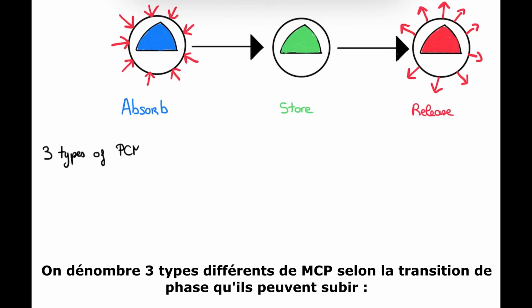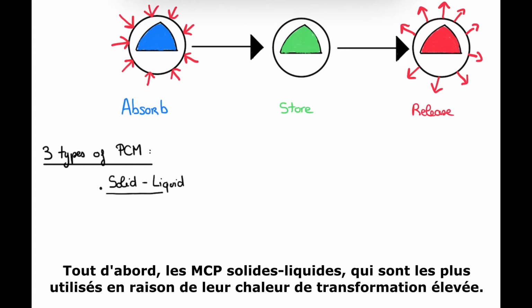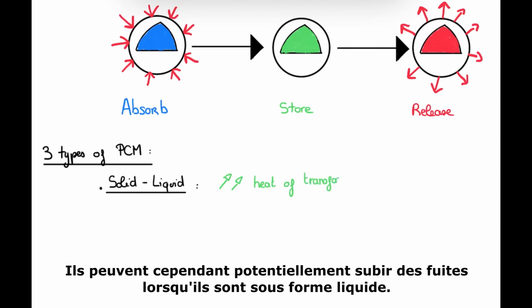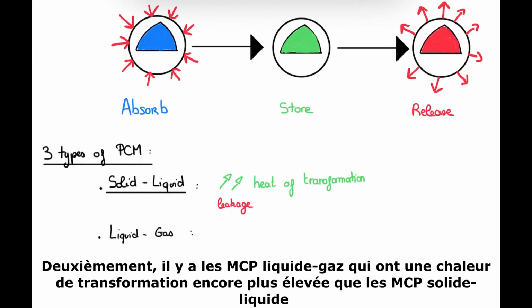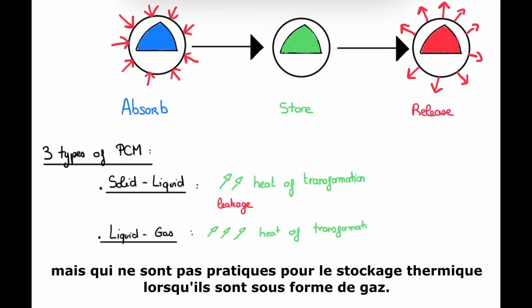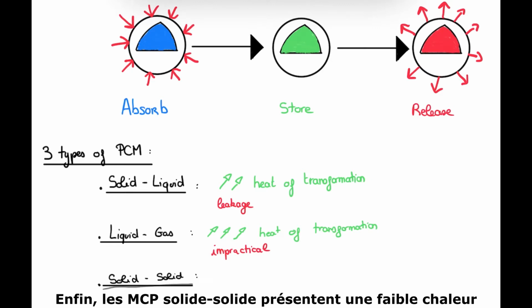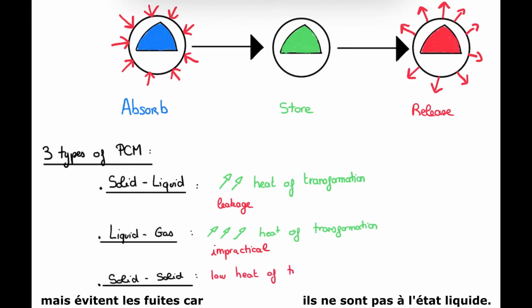We count three different types of PCM according to the phase transition they can undergo. First, solid-liquid PCMs, which are the most used due to their high heat of transformation. They can, however, potentially suffer leakage when in liquid form. Secondly, there are liquid-gas PCMs, which have even higher heat of transformation than solid-liquid PCMs, but are impractical for thermal storage when in gas form. Finally, solid-solid PCMs, which, while showing relatively low heat of transformation, ward off leakage as there is no liquid state.